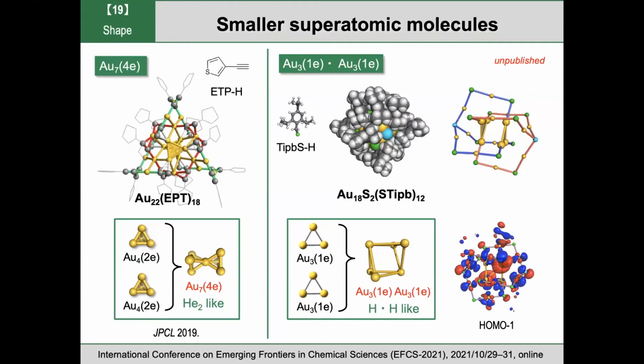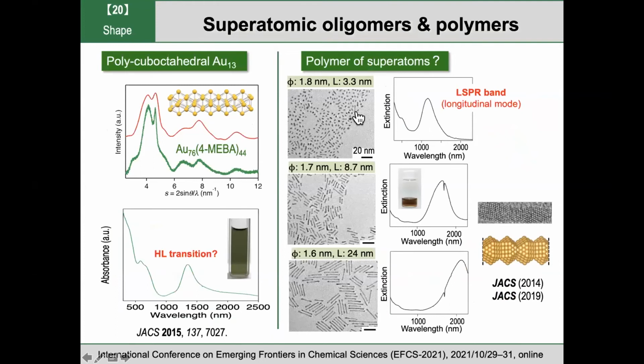We can also synthesize a slightly thicker wire structure like this. The high resolution TEM image shows that the structure is composed of spherical FCC packing. Interestingly, this very thin nanorod shows a very intense absorption band like this. These bands are localized surface plasmons along the long axis, so the electrons in the rod can oscillate collectively along the long axis. And the position depends on the length of the rod like this.